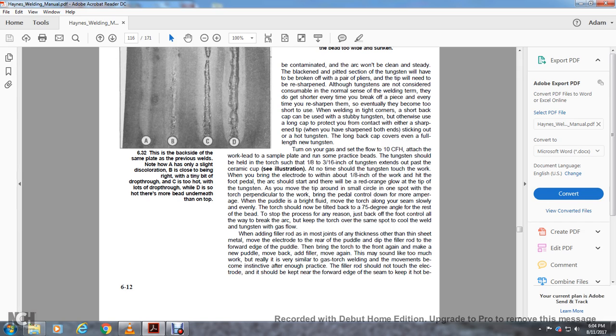To stop the process for any reason, just back off the foot control all the way to break the arc and keep the torch over the same spot to cool the weld and tungsten with the gas flow.